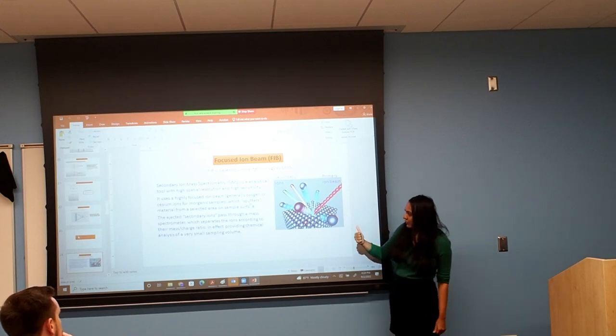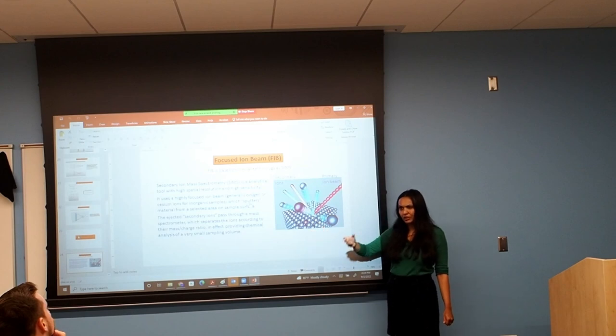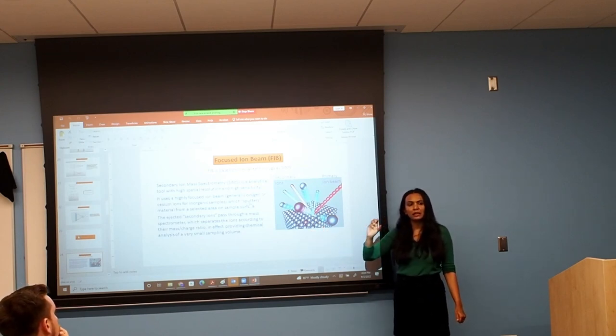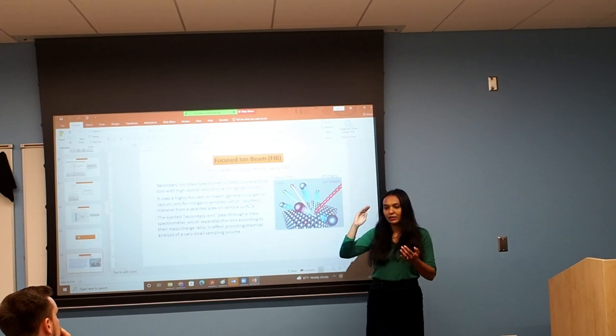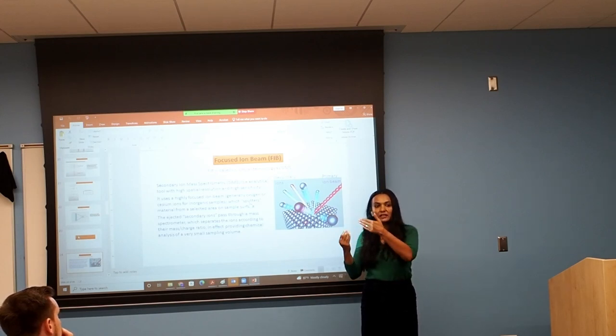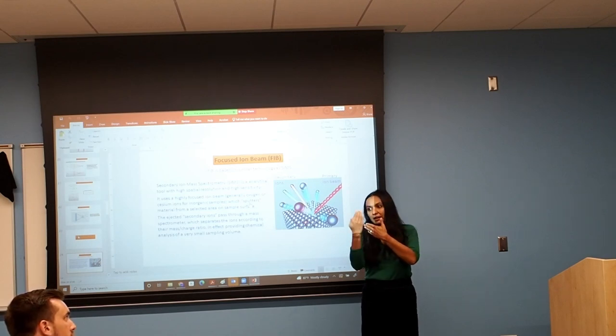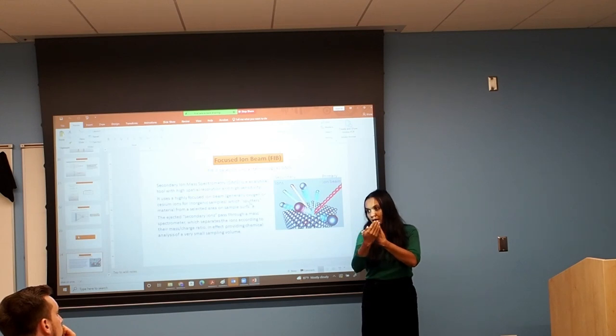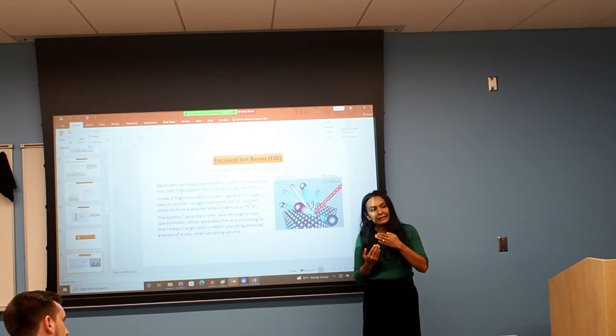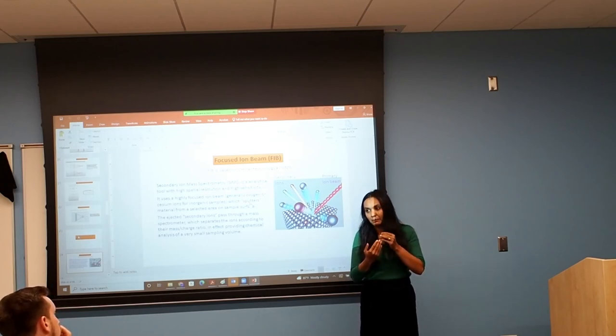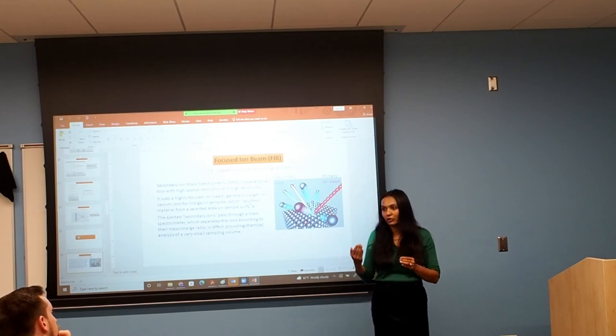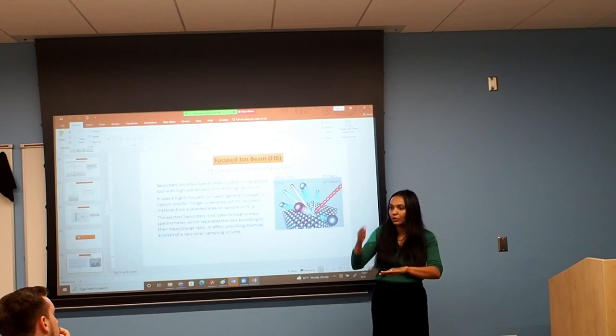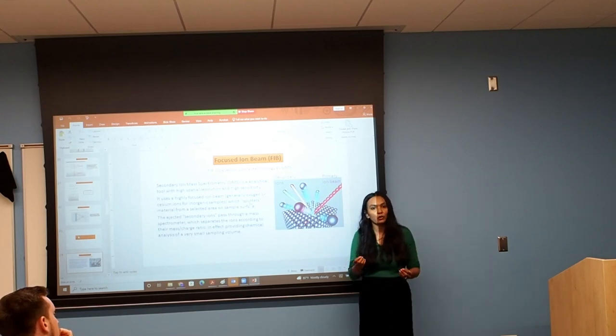When we start doing it, it is very easy. You have a very thick piece of metal, you are trying to grind it into a very thin piece, and you're using your ion beam, which simply takes it. We call it feathering, as you have seen feathers. If this is a sample, you put your ion beam in a way that the energy of the ion is so light that it literally removes it like this, especially at the end part. In the beginning you have a thicker piece, then it becomes very thin, and at the end step you keep the energy very, very low. That procedure goes for 30 minutes to an hour, and you do a feathering, and you remove it like this. You don't go boom, boom, boom. That is how you control the damage.